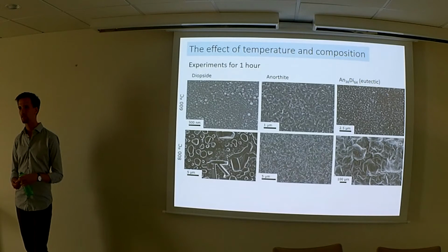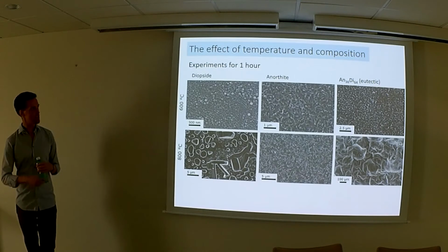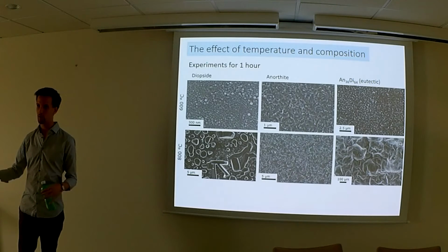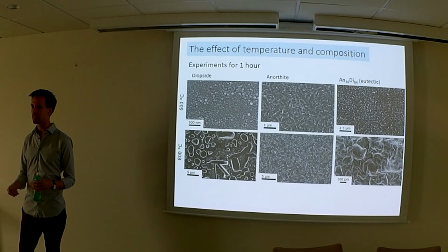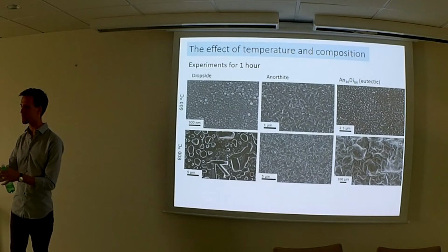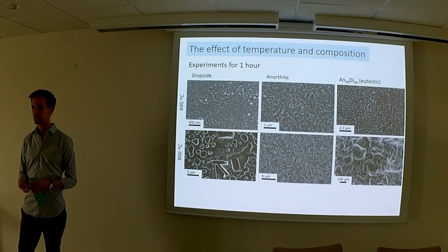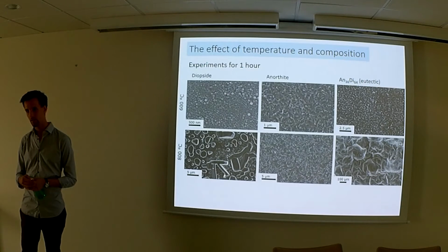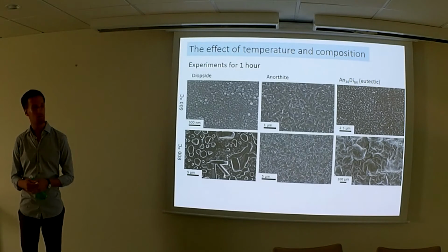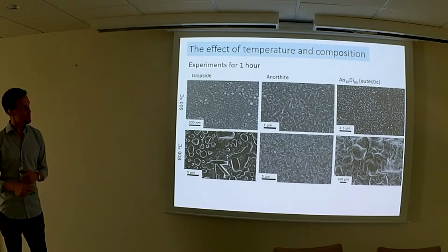On top of this is a polished glass, right? Yes, so all these glasses are polished down to a quarter micron. So it's not because there's some roughness there that causes different grains. It's because it's not the same phase. One is calcium bearing, in other cases, magnesium bearing silicate growing. So it's not the same.